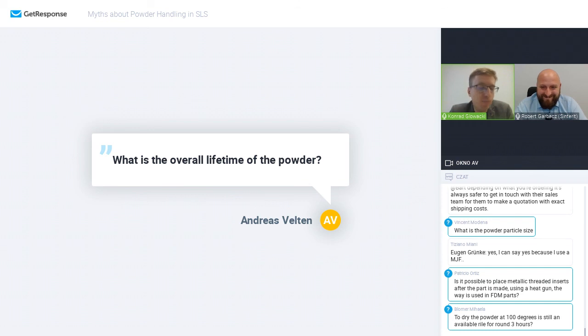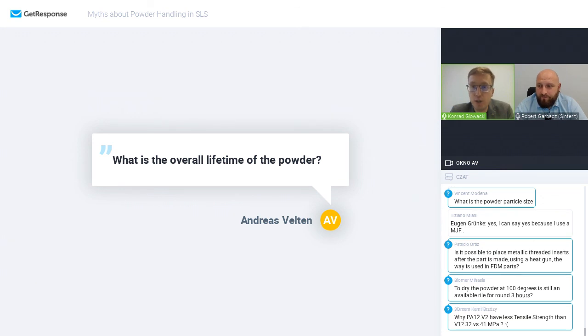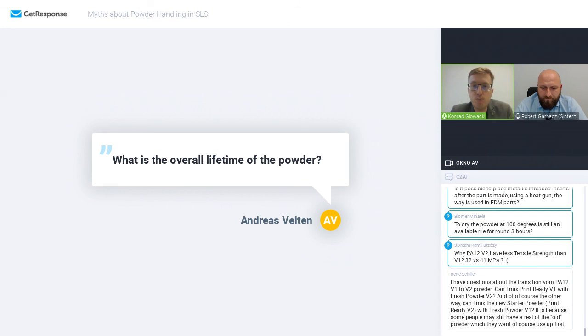So, lifetime of the powder. Essentially, the refresh ratio that we provide for PA12 is the refresh ratio that enables you to work with a powder continuously. But you need to keep in mind to minimize exposure to the moisture around, like when the printer stops printing and after the sieving process.